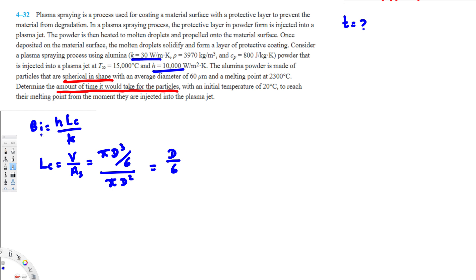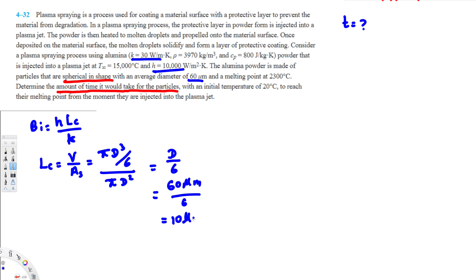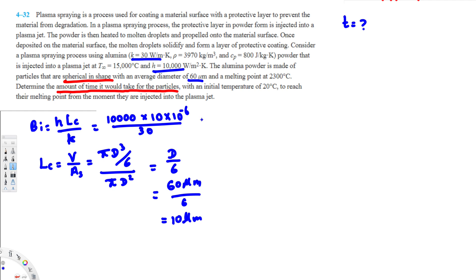We are trying to find whether the Biot number is less than 0.1 so that we can use the lumped system analysis equation. Now since we have Lc, we can find the Biot number. Lc = diameter / 6. The diameter is 60 micrometers, so 60 / 6 = 10 micrometers. Now we plug this into the Biot number equation: h·Lc / k = 10,000 × (10 × 10⁻⁶ m) / 30 = 0.0033.